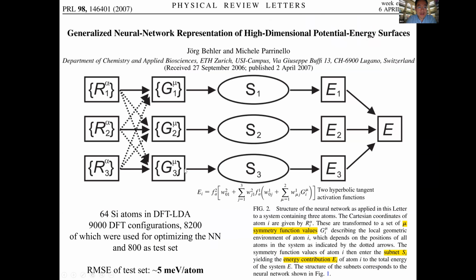And about 2007, Behler and Parrinello came up with this new neural network interatomic potential, where they basically have a two-layer neural network with a hyperbolic tangent as the activation function, and they generated 9,000 DFT configurations. And what is truly amazing about this paper when I first saw it was the error. It's 5 milli-electron volt per atom, which is much lower than the so-called chemical accuracy, which is 40 meV per atom, the typical error bar in thermochemical measurements.